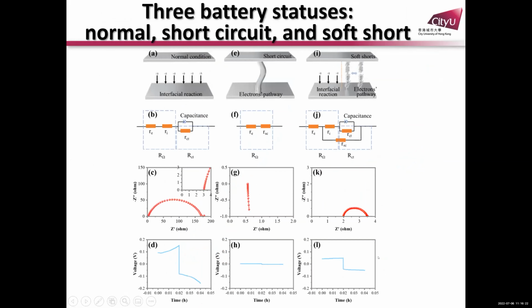So in a battery, generally we have a few states. One is the normal state of a battery, but another one, short circuit, is more like a resistance. The other one is called soft shorts, where we have battery behavior, and sometimes we also have some short circuit behavior, with one more resistance connected in series or parallel. If you check the impedance, this is normal, and this is almost no resistance, but this one still has impedance, though generally it's not quite normal. So this one gives us some illusion. It's not a normal status, but you can still collect some charge-discharge curves.